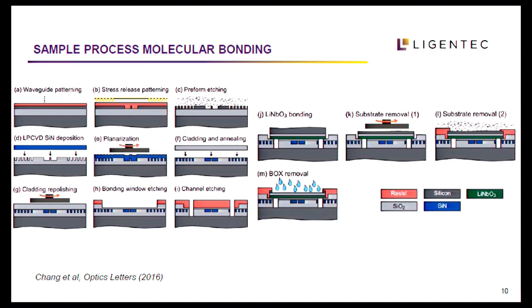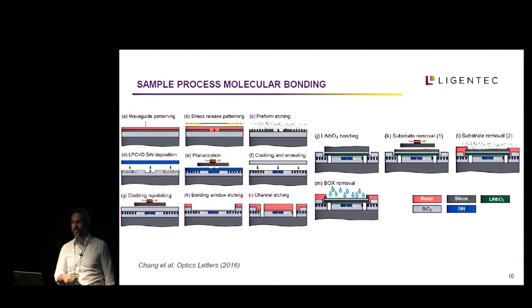But now the first thing that we need to notice is that cladding needs to be bonding quality. Bonding quality means that your roughness is ideally better than 1 nanometer. So we need to polish it at some stage. For example, in this integration flow from 2016, we just bond here. But then you need to thin down this layer, and accurately stop just 100 nanometers away from the silicon nitride. And I can tell you that this is difficult to control across the whole wafer with certain tolerances, so all the devices will work. So we need to be very careful.